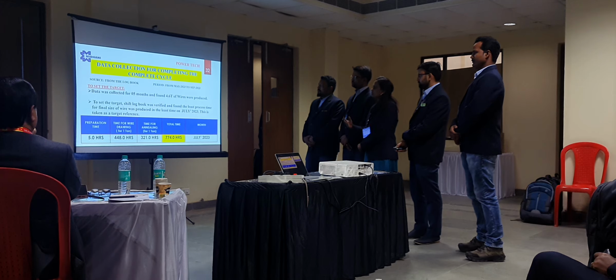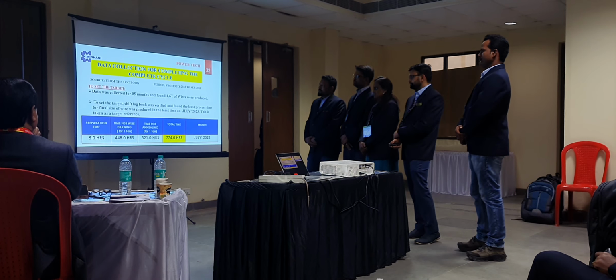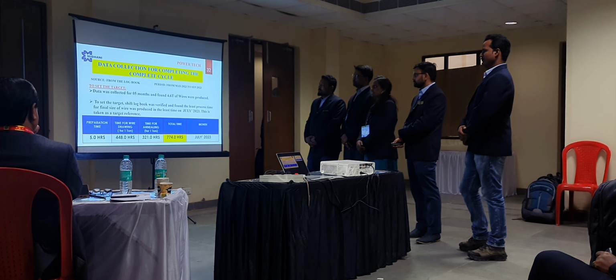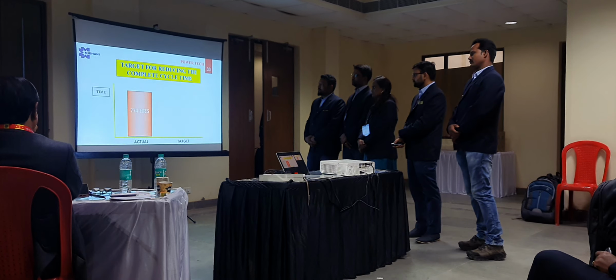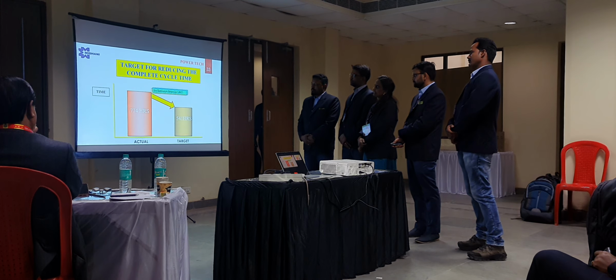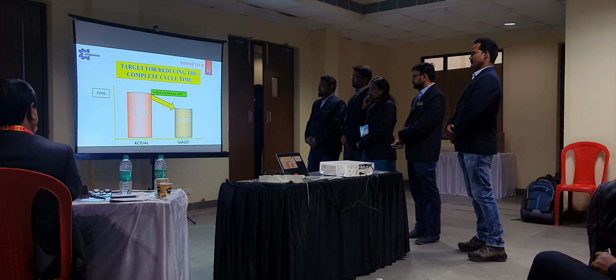Among these, the highest productivity we achieved was in the month of July, that is 1.05 ton. To produce that 1.05 ton, it takes 774 hours. This is the least process time. It is taken as the target reference. We plan to reduce the complete cycle time by 30%, that is 540 hours.